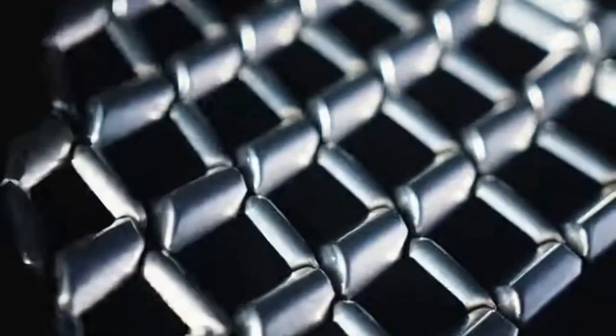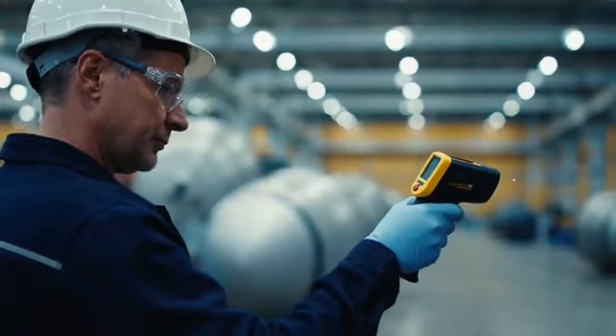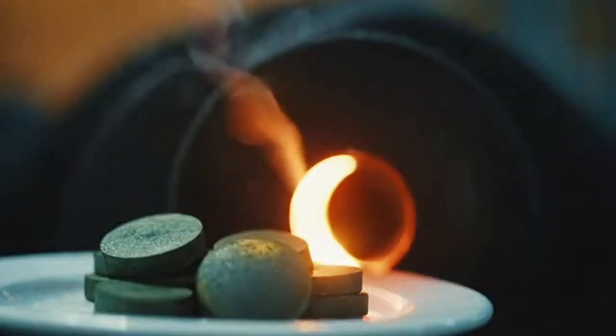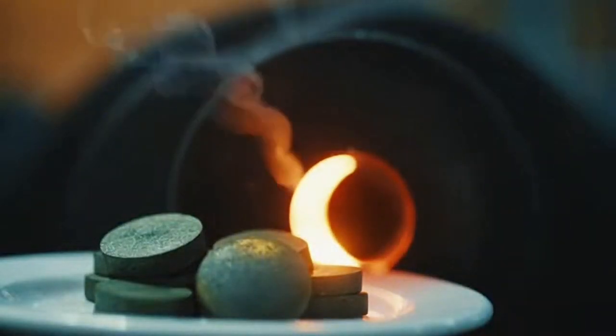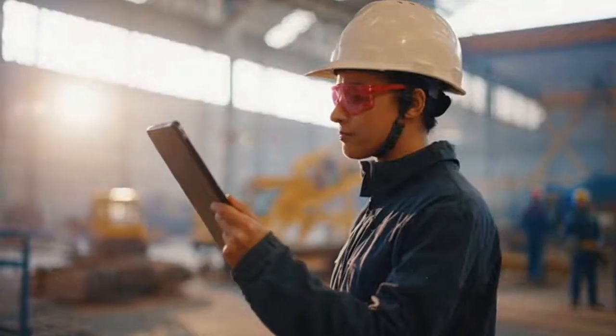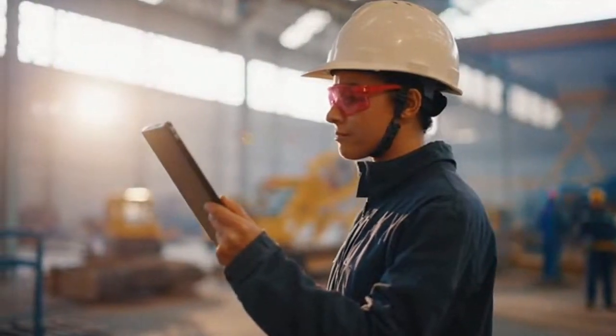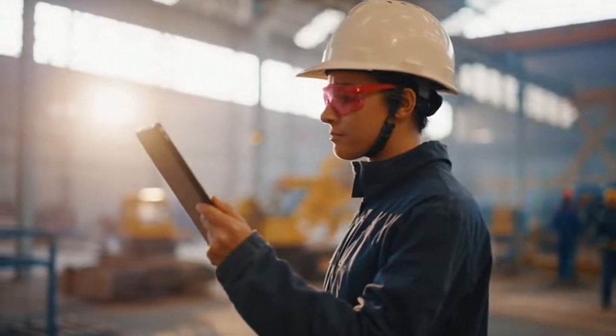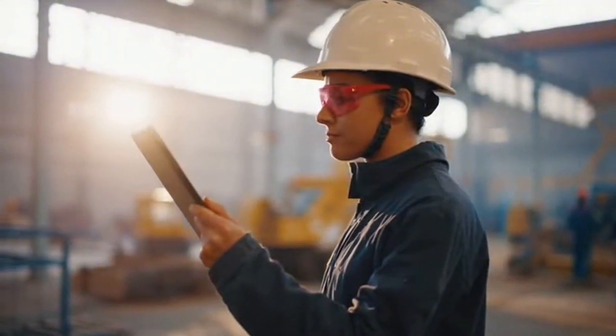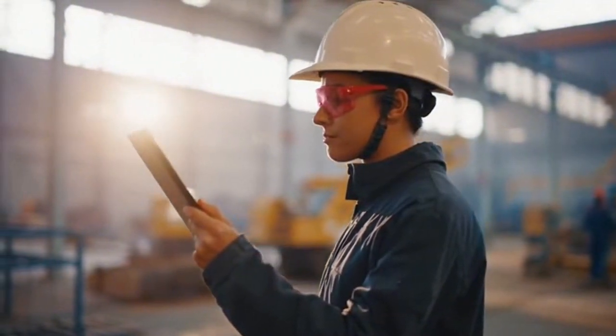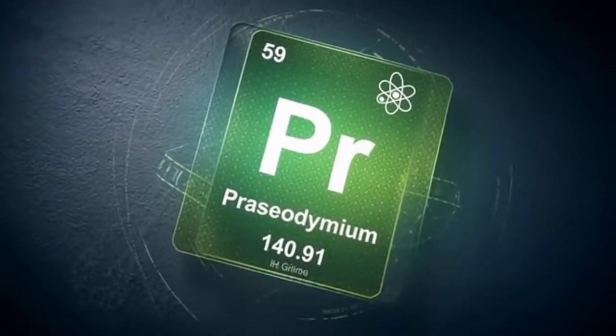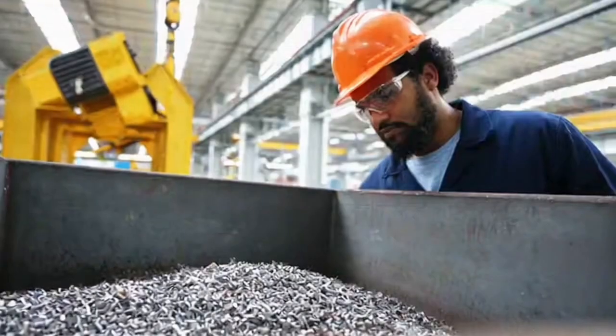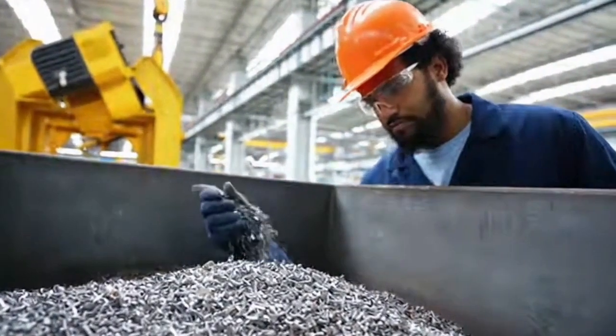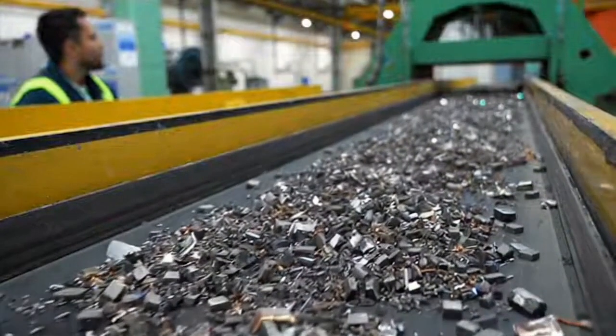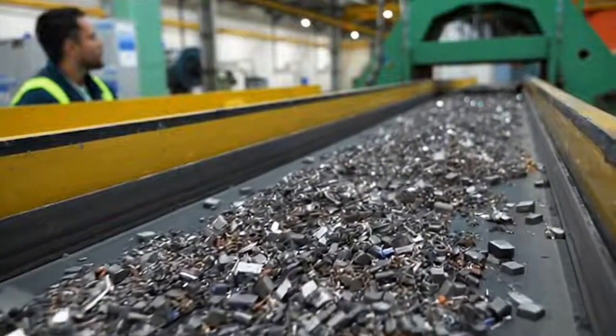Recycling is where optimism meets metallurgy with a thud and then stands up again. In-process recycling works beautifully. If you are machining magnets, you catch the swarf, you hydrogen crack it to pieces, you remill, you blend back into powder, and as long as oxygen and carbon are controlled, you are back in business. The closed loop is tight because the alloy is known, the contamination is manageable, and the timing is immediate.